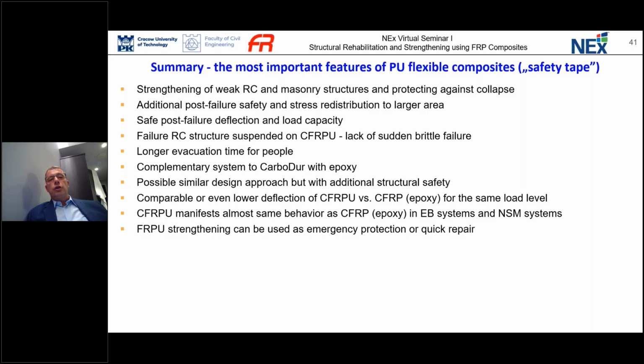A failing reinforced concrete structure, when it is strengthened with carbon fibers and polyurethanes, is hung on this composite material, and it is protected against sudden brittle failure. So this is very promising because it gives time for evacuation of people, and also gives authorities time to decide what to do with this kind of structure, if it should be supported, or maybe can be repaired or strengthened in another way.